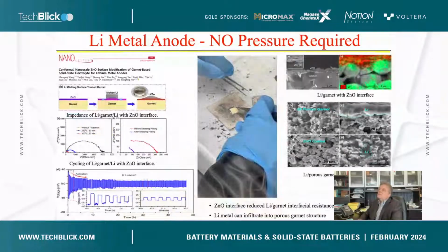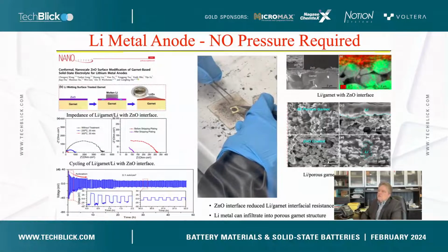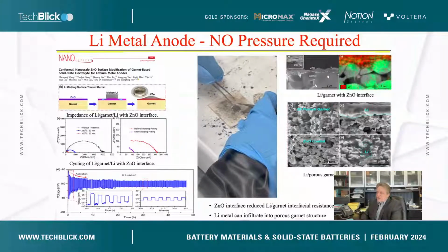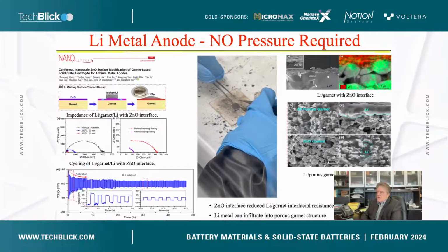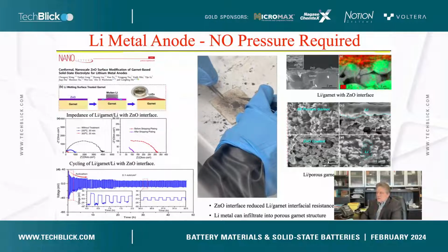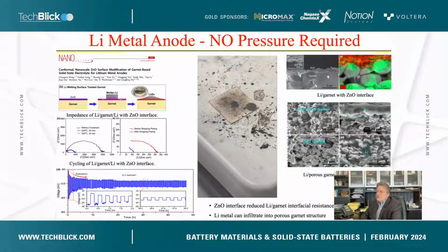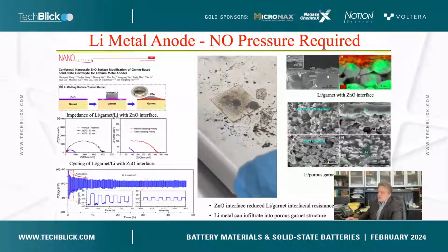To go even further, we want to expand the interfacial area by having a 3D architecture. You're seeing that in this paper here, where we have a porous microstructure, and we're just putting that on top of a hot plate which has some lithium on it. You'll see how fast the lithium metal will infiltrate into the pores by capillary action. It really just sucks right in there and results in a great interface between the lithium metal and your solid electrolyte at room temperature.